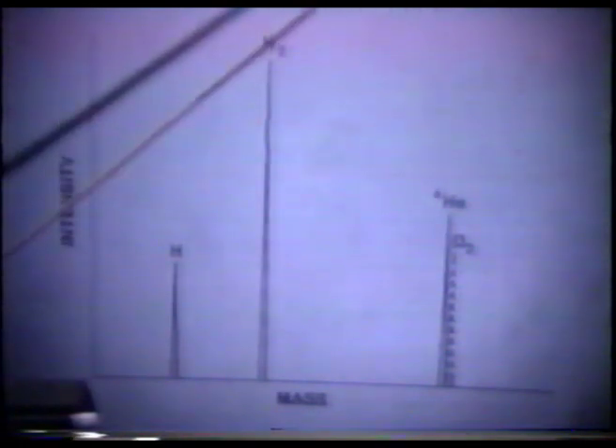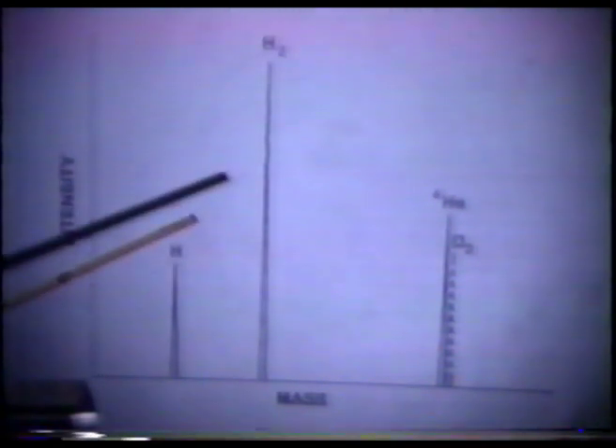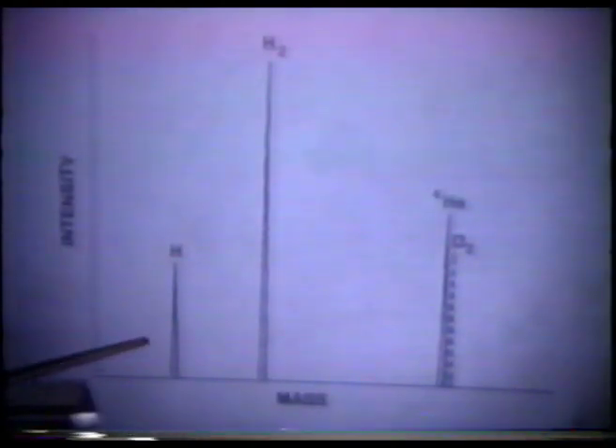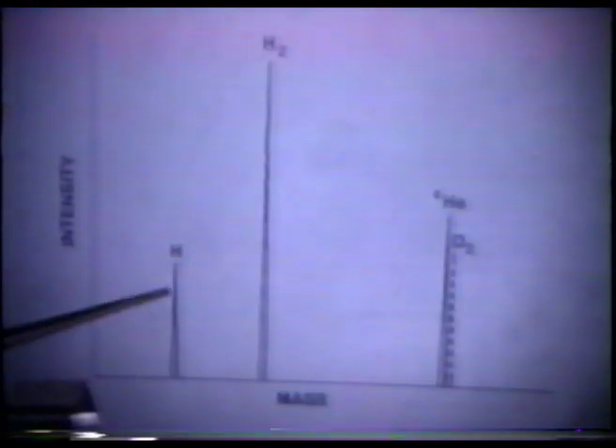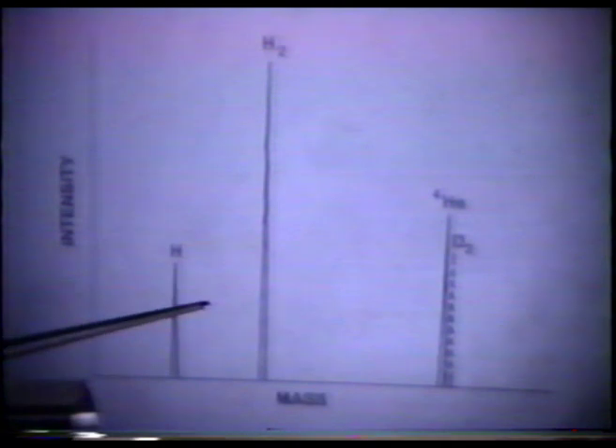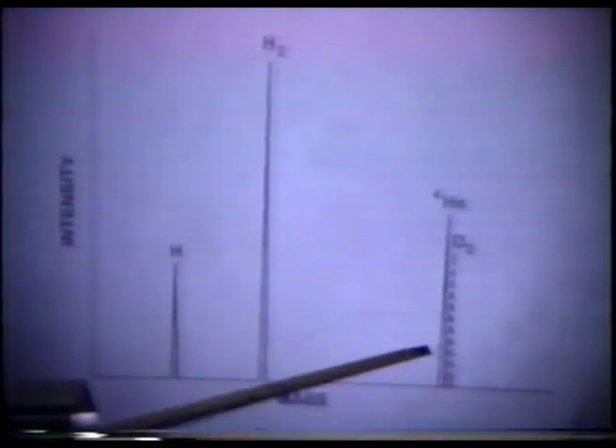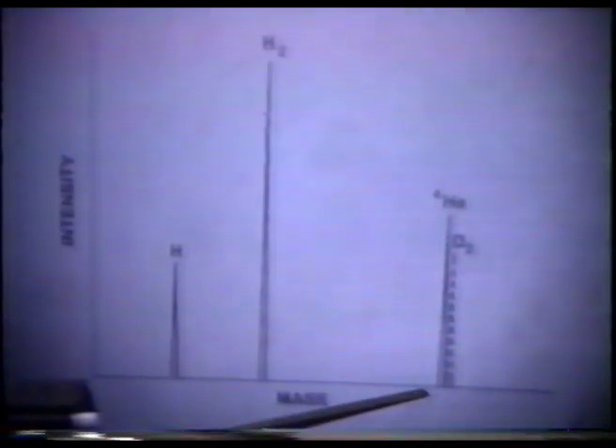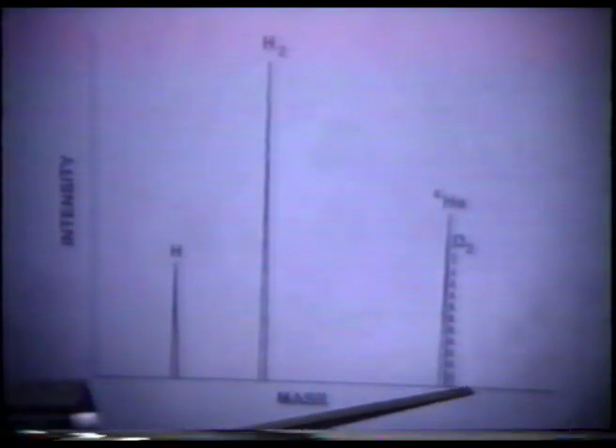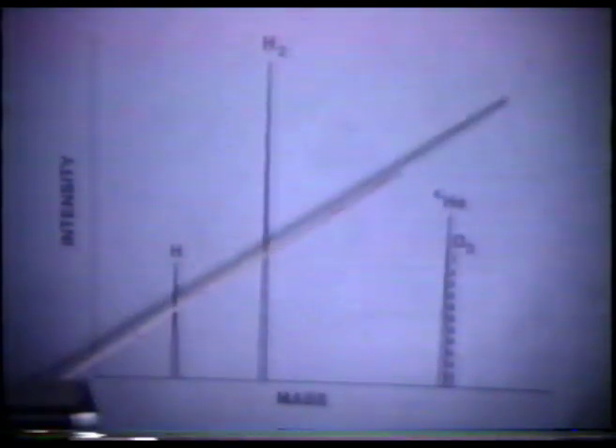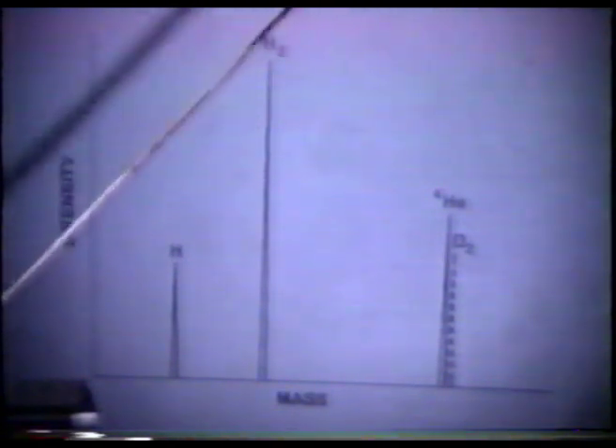An example of what a mass spec result would look like: we always ran this on the highest sensitivity of the mass spec. There was always some contamination of hydrogen, either from moisture in the mass spec or hydrocarbons in the mass spec. You couldn't get away from, on the high sensitivity, seeing a little bit of hydrogen. Had nothing to do with our experiment. It was just always a residue of hydrogen in the mass spec. But we would see the helium peak, and we could baseline separate, if any D2 did get through, which it did occasionally, the helium-4 from the deuterium gas. And furthermore, you could identify the two if you had any question by lowering the ionization voltage and tell which one was which.